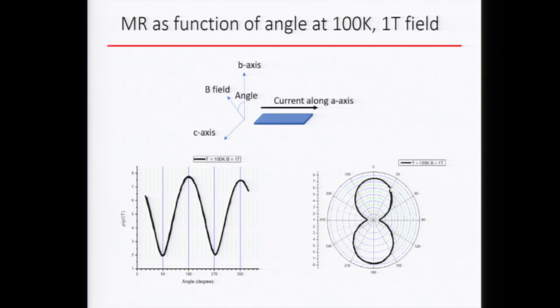With a weak field, let's say at 100 Kelvin, you see some large but still rather conventional magnetoresistance, two-fold oscillation as a function of angle, right? You have larger magnetoresistance for field out of plane because your mobility is higher in plane and the effective mass is lighter in plane. When you rotate the field in plane, you have less magnetoresistance because the effective mass is higher for the interlayer direction. So you have this two-fold behavior.